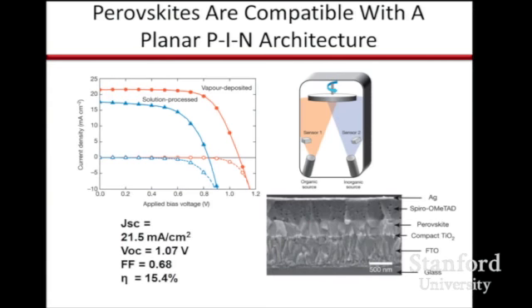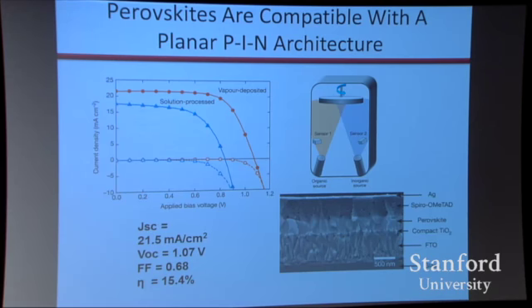But Henry Snaith has shown us that you don't need the titania. You can just make a planar PIN junction. Here you do have titania, but not a porous film. You just have a solid film of titania that's N-type. Then you have undoped intrinsic perovskite, and then you have a P-type organic hole transporting layer. And this works very well too, with 15.4% efficiency.